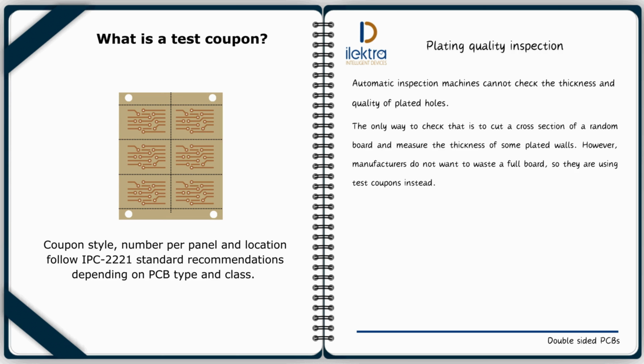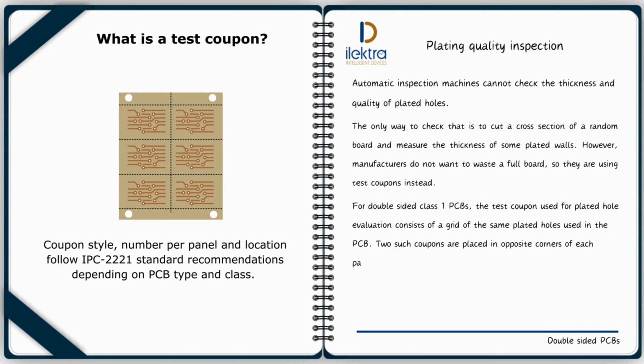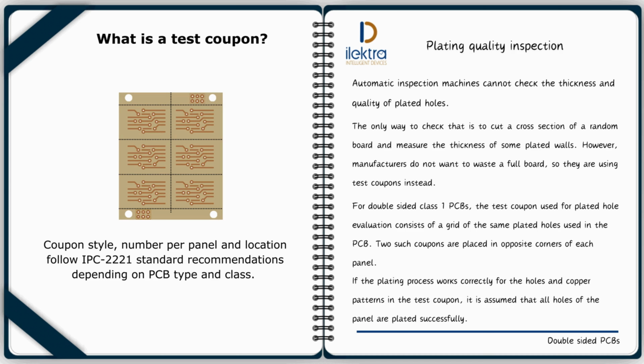for the coupons. For double-sided Class 1 PCBs, the test coupon used for plated hole evaluation consists of a grid of the same plated holes used in the PCB. Two such coupons are placed in opposite corners of each panel. If the plating process works correctly for the holes and copper patterns in the test coupon, it is assumed that all holes of the panel are plated successfully.